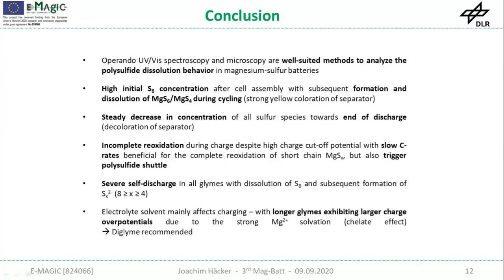Yeah, in fact, that's not a practical voltage range. So I mentioned before, 3.5 volts during charge is quite high, and also 0 volts during discharge is quite low. But we want to examine the edges where those species are reduced or completely reoxidized. So we want to stretch this window a bit, and this gives insight for further cut-off voltages. So in fact, the cathode has to be improved, so the overpotentials have to be minimized. That's true, but also to widen this window to investigate where those species are reduced or oxidized gives a hint for further definition of the cutoff potentials. Hope this answers the question.